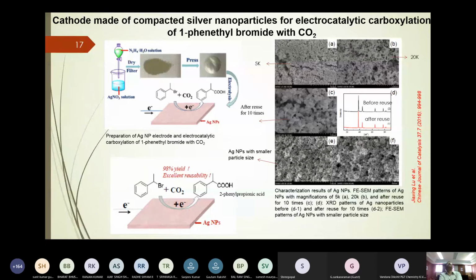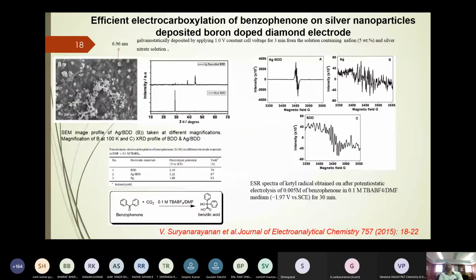Here they use silver nanoparticles for the conversion of phenylethyl bromide to 2-phenylpropionic acid, which shows a high yield. Okay. Now we can go for the next example. There we can convert benzophenone to benzilic acid by using silver nanoparticles deposited on a boron doped diamond electrode. Actually, this is what we have carried out in our laboratory. There we have published in the Journal of Electroanalytical Chemistry, in the year 2015.